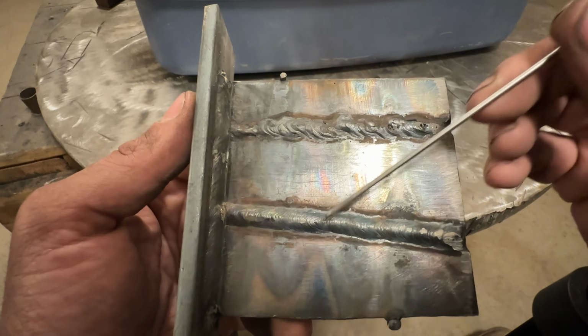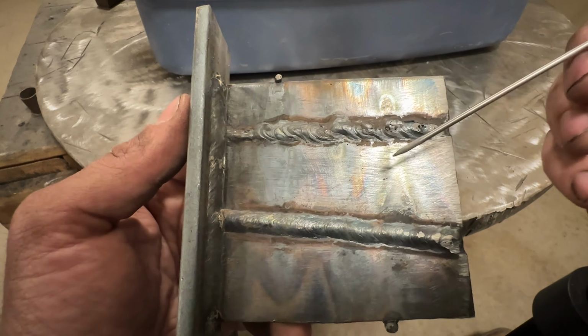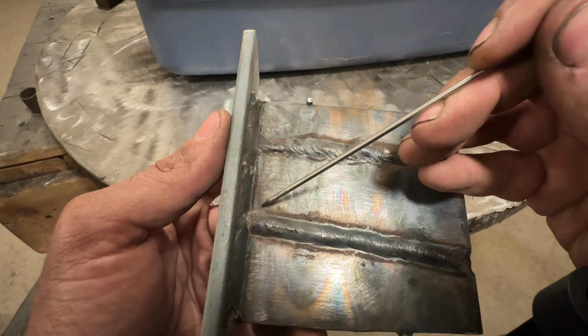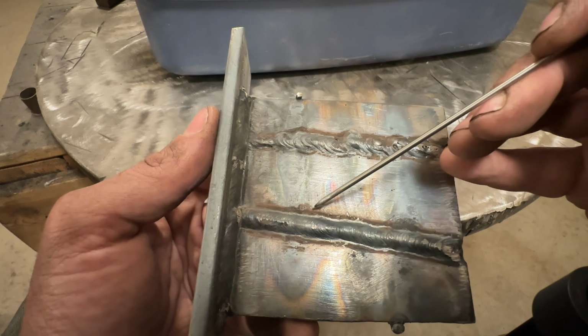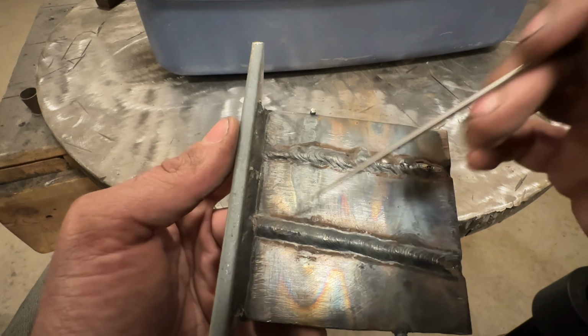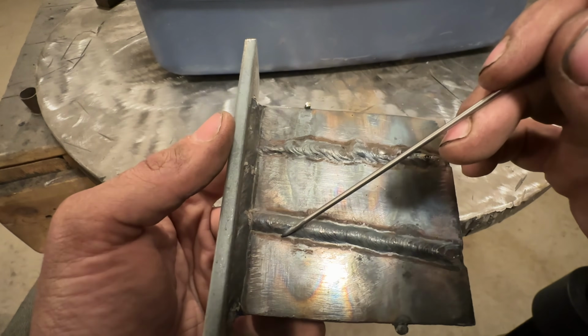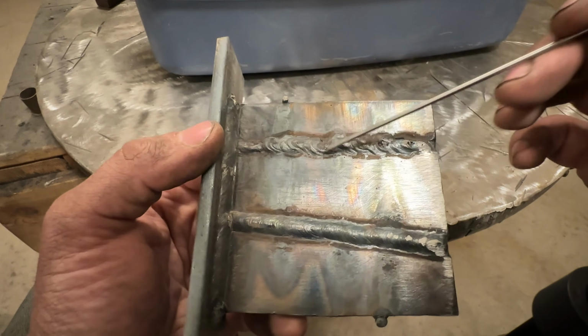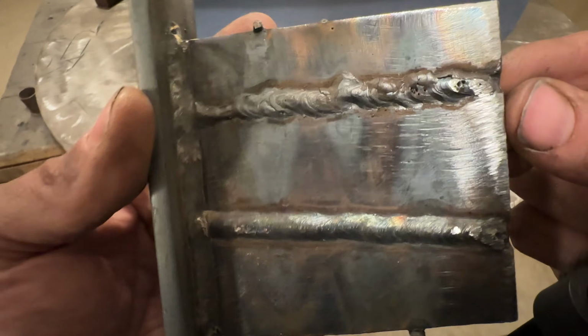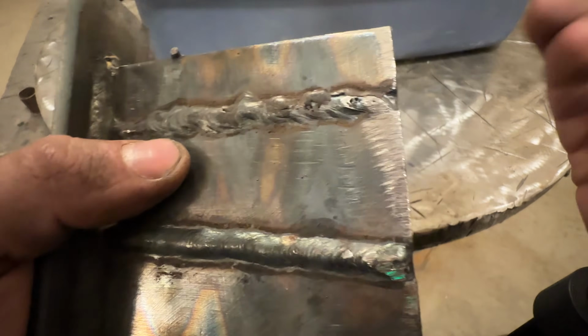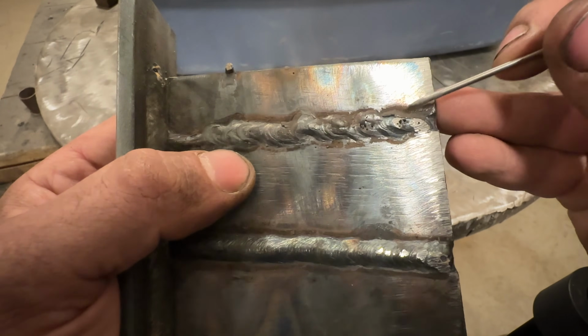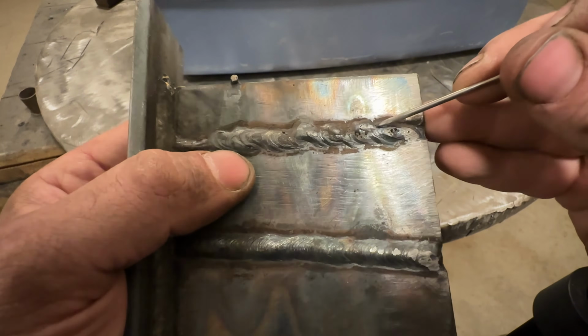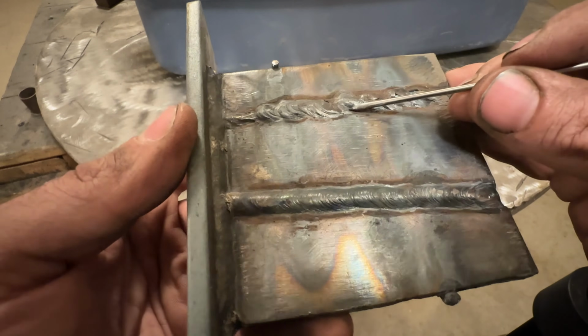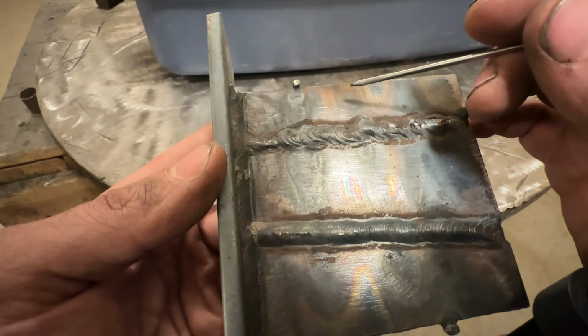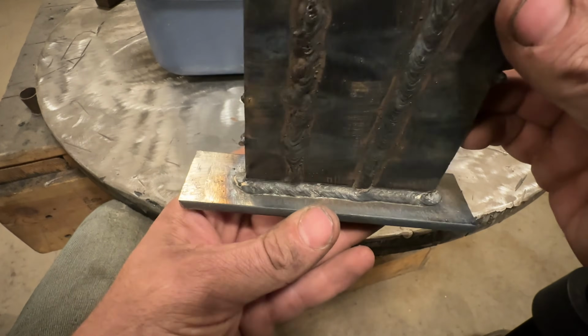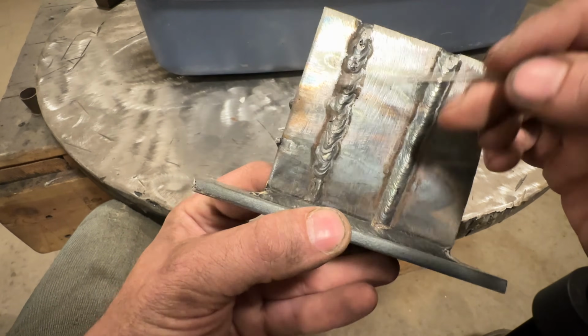That's the difference. There's no magic between these two. It's just this: my travel speed stayed the same start to finish. My rod angle, my arc gap, all the same for that. This was all over the place, and look what you get with that. We can see other weld defects. We have evidence of porosity here. There's undercut here. I mean, it's an ugly looking weld. There's no way to put it but that.